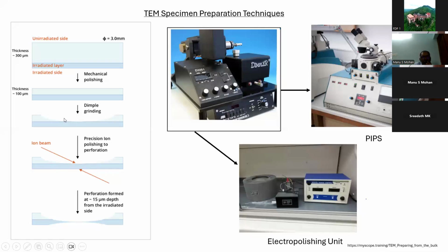So then you have to thin it down, and once you dimple it, you have to take it to either a precision ion polishing system or an electropolishing unit. This is called precision ion polishing, meaning you expose the specimen to argon ions, which will be continuously bombarding it.